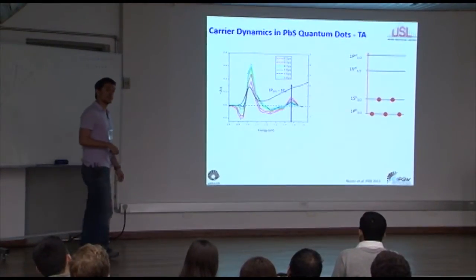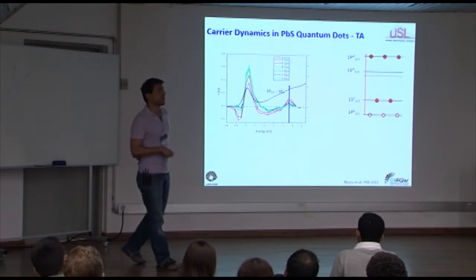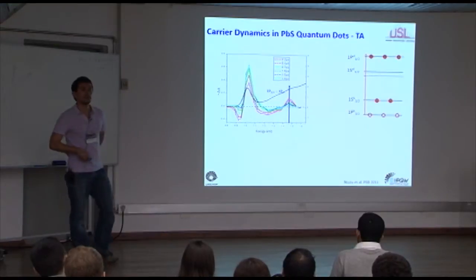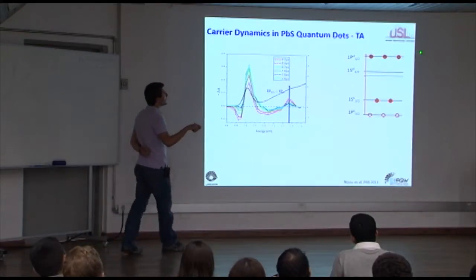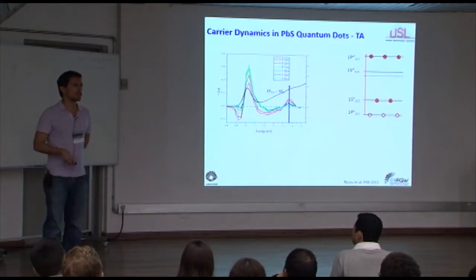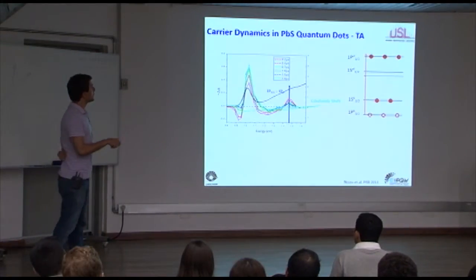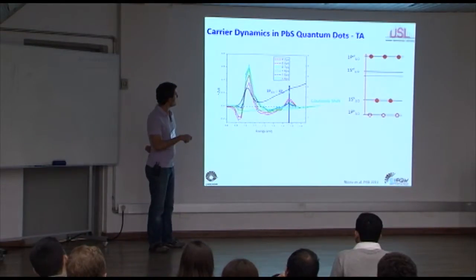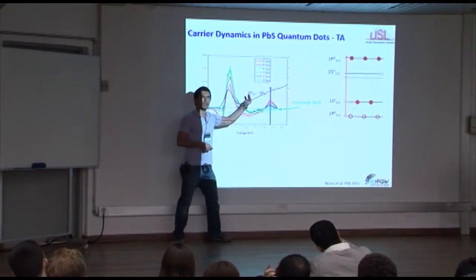I can use this one also. It has also the schematic. So basically, what we're doing is simple. We're taking the electrons and putting them up there. We're pumping it to a higher level. So in the very first few picoseconds, it's going to populate a higher level state. First of all, as it is up there, it causes a Coulomb repulsion, which makes the energy states shift. So the whole band gap comes to lower energy.